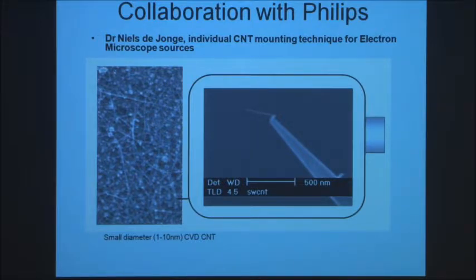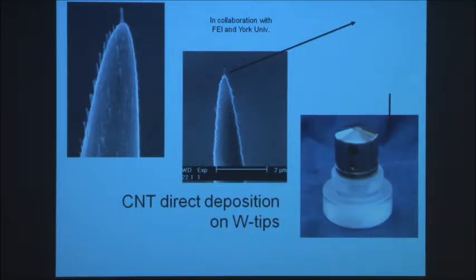So it was quite a neat idea, but then we decided a better idea would be to actually grow the things in situ. And so what we did is we found a new way of taking nanotubes and growing them on top of an individual tungsten tip. Now, how you do that is you have a PECVD system, and if any of you know about PECVD, if you've got something metal sticking up in the middle of a plasma, the plasma etches it away, and you actually get the stuff etched rather than grown. So that doesn't sound too clever.